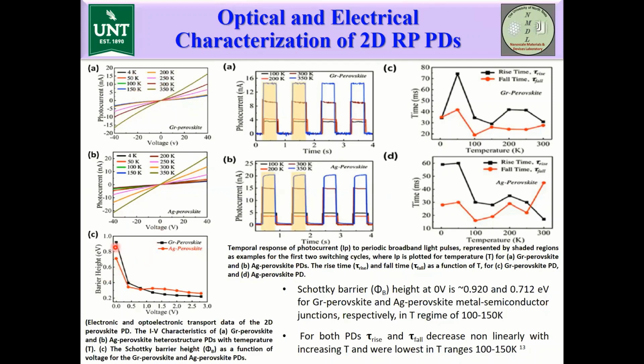Here you can see the barrier height variation with voltage for both graphene and silver perovskite, and we have used this to calculate the Schottky barrier height at 0 volt, which is around 0.92 electron volt and 0.712 electron volt for graphene and silver perovskite photodetectors in the temperature region of 100 to 150 Kelvin.